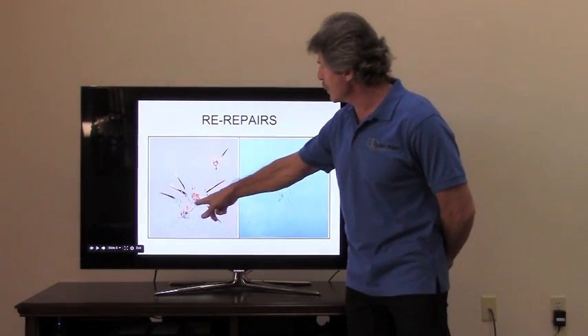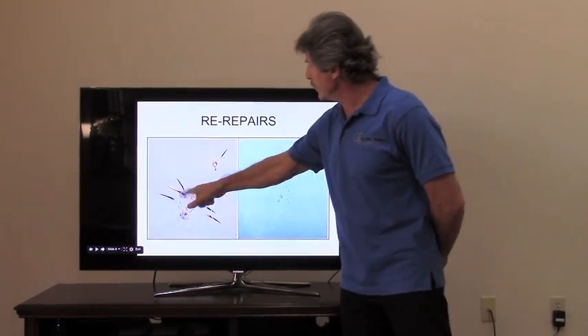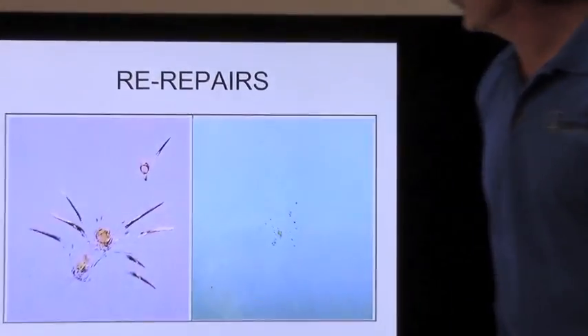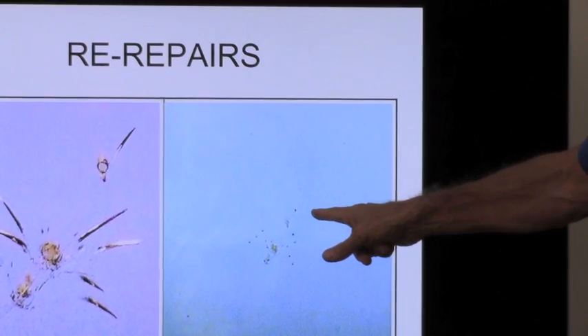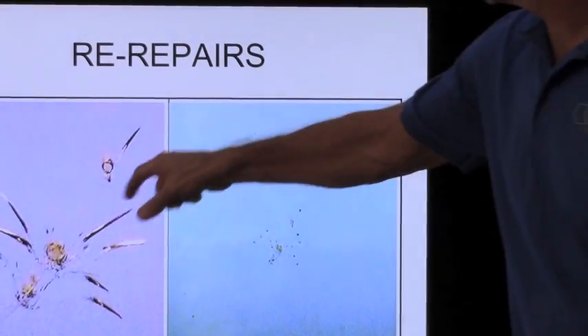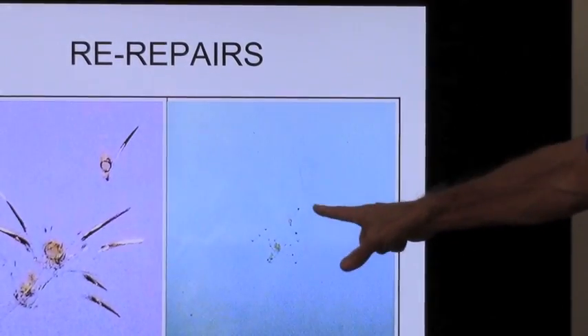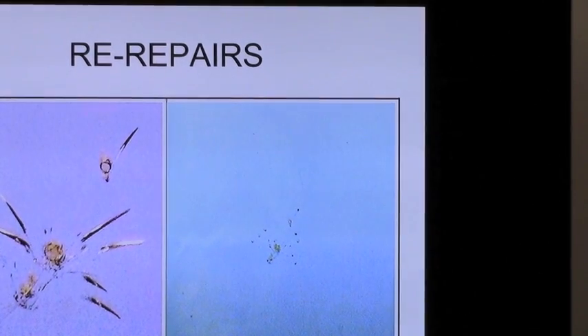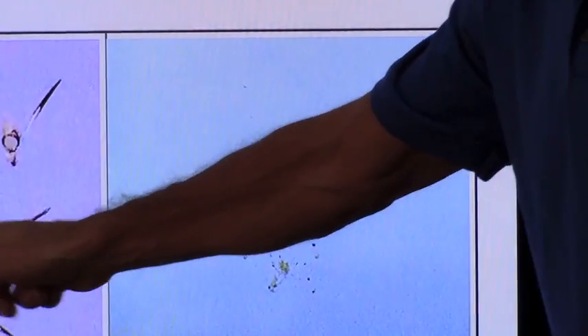Here's an example of one. This one came into our shop. Now you can see they didn't get resin into any of those legs. But what I did is I drilled and tapped the bullseye onto each one of those legs, and that was the result. You can see that's totally bonded. Drilled, tapped a bullseye, filled it up with about a 20 CPS resin, and cured it under pressure. Okay, so I took a mess of a repair and then did a re-repair.